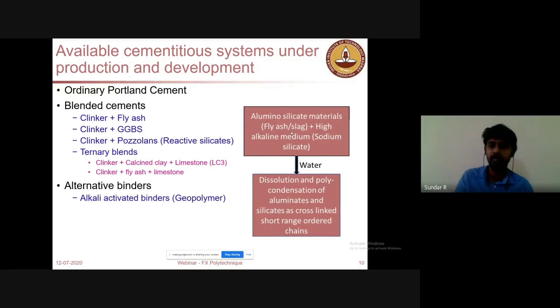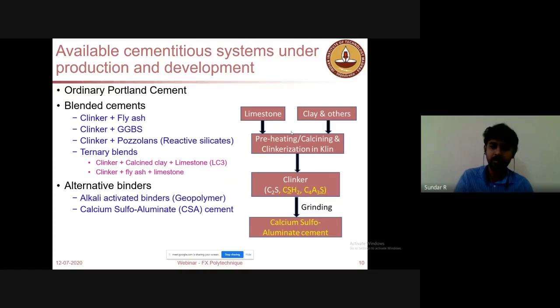Here it will be mostly devoid of OPC. They mostly use fly ash and slag, and then they keep them in an alkaline medium. That alkaline medium in combination with these aluminosilicate materials, which are essentially slag and fly ash, will polymerize and form this cementitious material, that is geopolymer. And then calcium sulfo-aluminate cement.